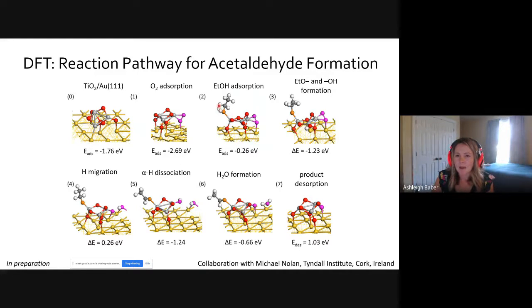In this next step, the acidic hydrogen dissociates and forms ethoxy on the surface and leaves an OH on the titanium nanoparticle. Hydrogen can then migrate over to form an OH on this oxygen. And then finally, the alpha hydrogen dissociation is able to occur, that hydrogen again also migrates over so that we're able to form water. And then the acetaldehyde is able to desorb.